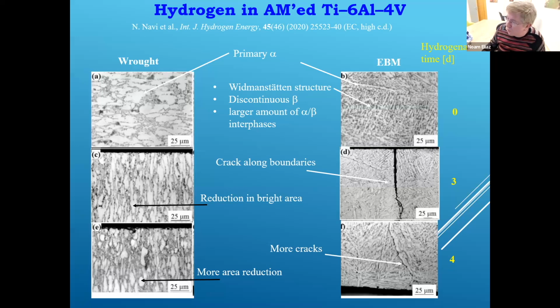I won't touch it. So what you can see here from one of our papers, you can see the microstructure on the titanium 6-4, the wrought alloy on the left-hand side, the electron beam melted powder bed fusion on the right-hand side. Of course, the microstructures are different, but then you can see the microcrack that propagated in the absence of any external load, just during the hydrogenation. We got further mechanical tests and others later to support this.